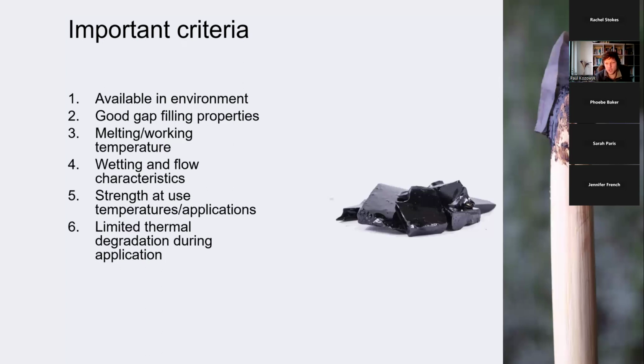Finally, it should have a limited thermal degradation during application. It's being applied by heat, and the only source of heat is an open fire in this case. If the adhesive is negatively affected by too much heat, it's going to be very difficult to apply without destroying the adhesive. So highly volatile materials, for example, are not very well suited to this because you warm it up and it's going to either combust or break down.